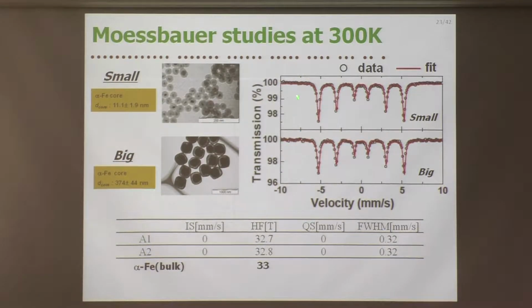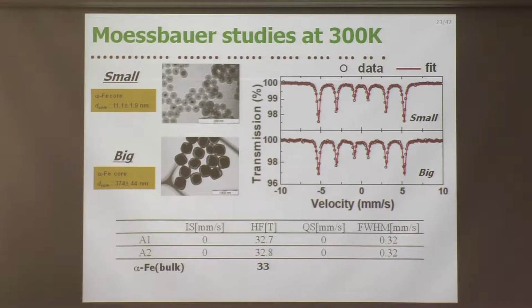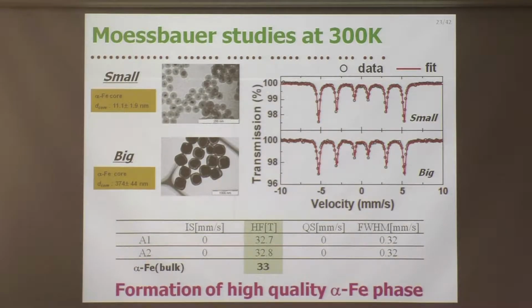Here shows the results from together with the fit. As you can see, the data are well fitted by a single alpha iron pattern. I will skip the details, but here shows the fitting parameters used. The close resemblance of the hyperfine field values reveals that the quality of the alpha iron phase obtained was very good.